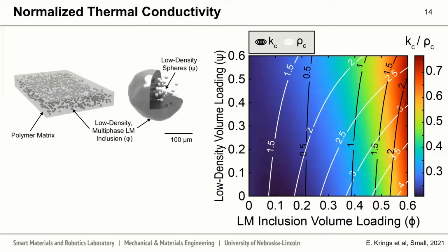Finally, we can create a design map from this. We see the volume loading of the low density phase on the y-axis within the multi-phase filler, and on the x-axis, the loading of this multi-phase filler into our elastomer composite. The color map shows this ratio of the thermal conductivity of the composite to the density of the composite. On top of this, we can draw lines of constant thermal conductivity, shown in black, or lines of constant density, shown in white.